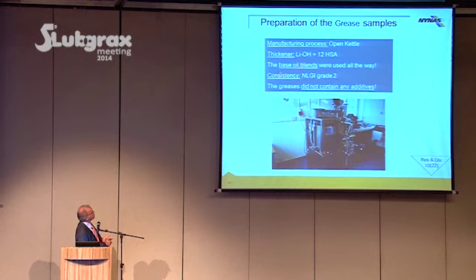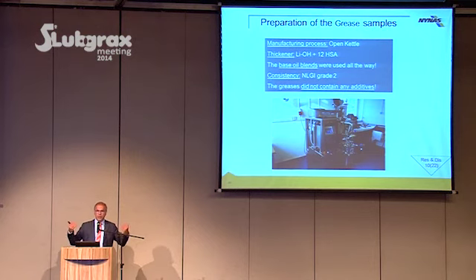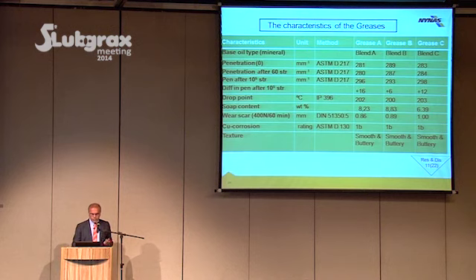Conventional greases, of course, as you know, is lithium grease plus 12-hydroxystearic acid. So we use it in open kettle form. The consistency was NLGI grade 2, which is very common. And we didn't use any additives, because the idea was to evaluate the impact of the base oils on the final formulated greases. So these are some of the properties which we generated on the greases.